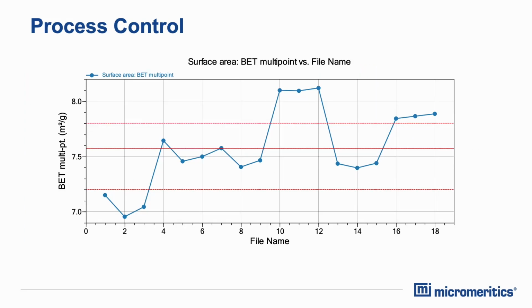For this example, I want to focus on BET. So why is the surface area important for the final electrode? Increasing the surface area of the electrode, for instance, could result in improved efficiency of the electrochemical reactions and can therefore facilitate the ion exchange between the electrode and the electrolyte, especially within an anode, as higher surface area permits shorter diffusion path to the lithium ions between the graphite particles. On the other hand, lower surface area materials might be better suited for improved cycling performance, resulting in longer battery lifetimes.